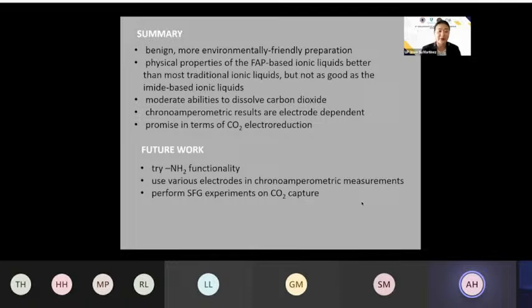And so in terms of future work, we're thinking of synthesizing amine functionalized ionic liquids. Perhaps this will work better than the other ionic liquids because amines are normally used for carbon capture, at least for carbon dioxide solvation. And then what we're doing right now is actually using various electrodes in our chronoamperometric measurements and determining, apart from platinum, whether other electrodes are actually better at doing this. And of course, hopefully in the future, we will be able to perform SFG experiments on how ionic liquids are able to capture carbon dioxide from the headspace.